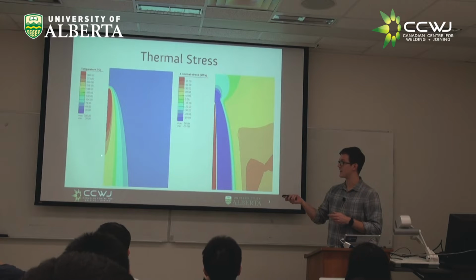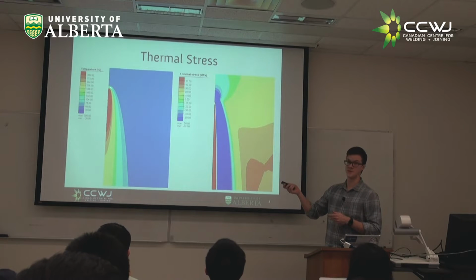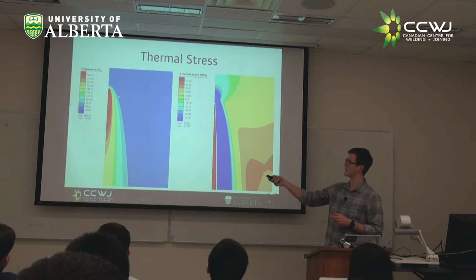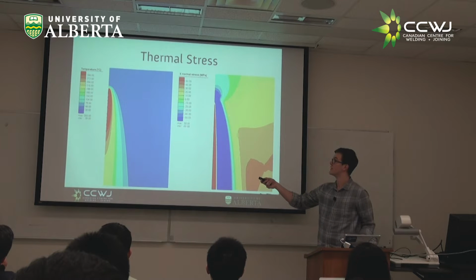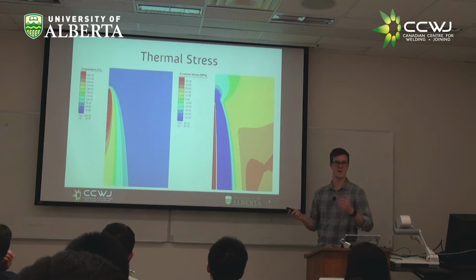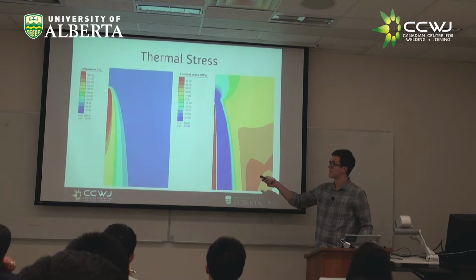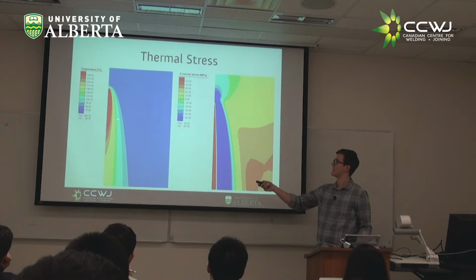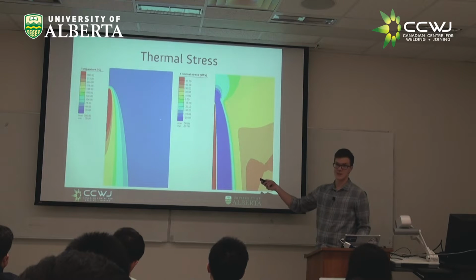If you're moving from here, this would be where your weld heat source is right now. And this is the temperature field that's flowing away from your heat source. So right at the tip of your heat source is where your maximum temperature is going to be. So I've cut this here at 300 degrees. You can imagine at the point of your heat source, you're way, way hotter than 300 degrees. You're up near melting temperature. But as you move both further away behind the weld and across the plate, your temperature decreases.